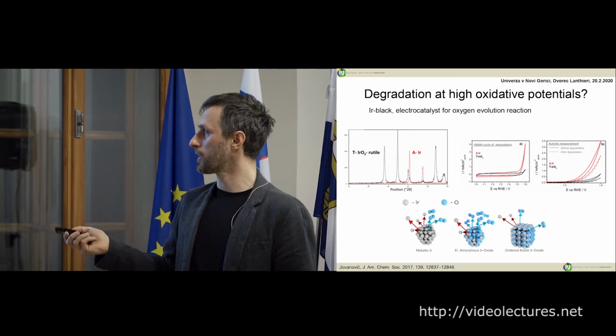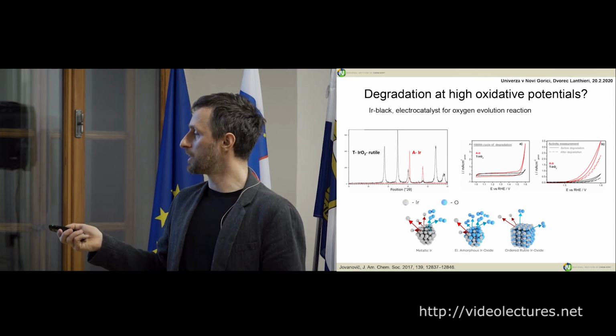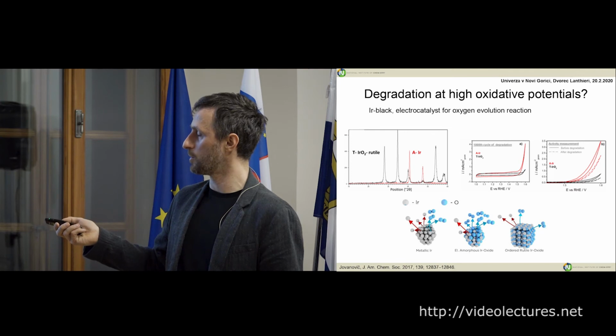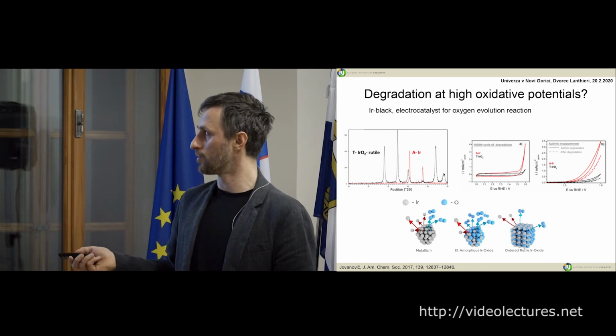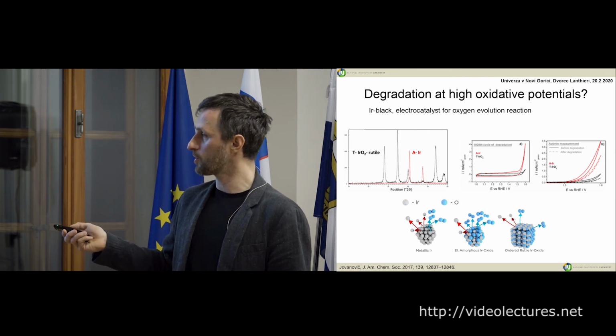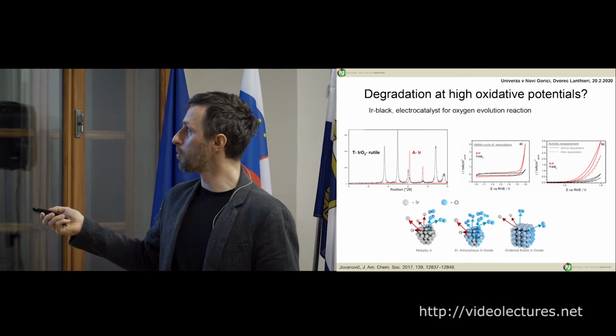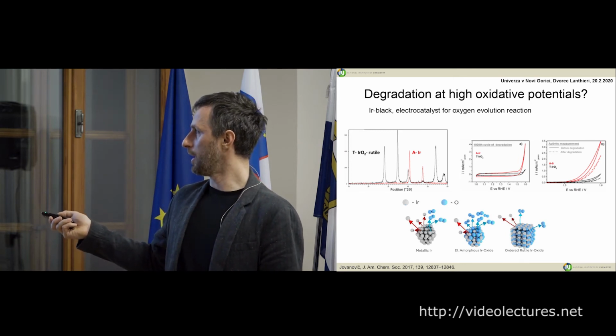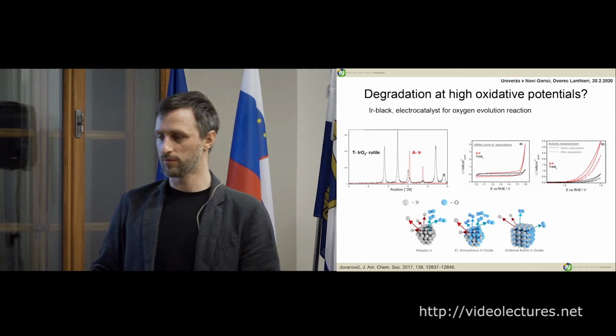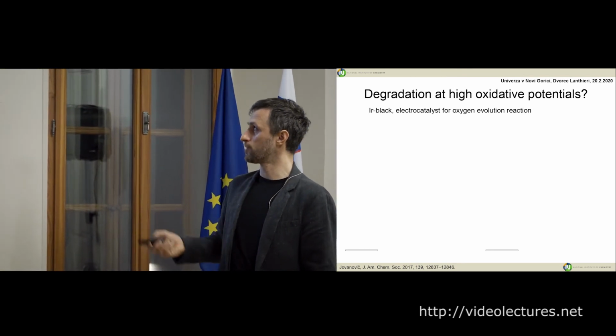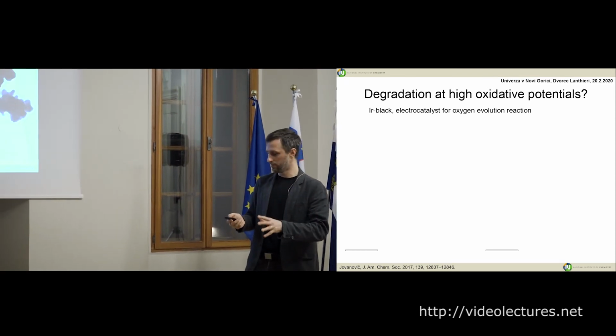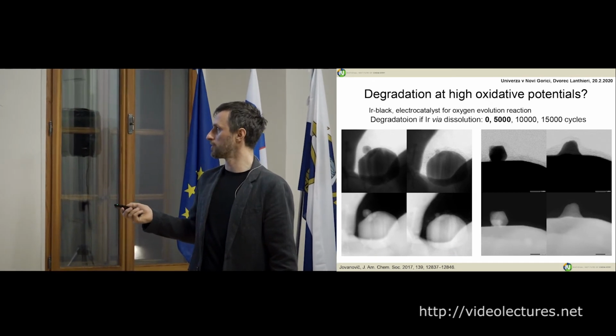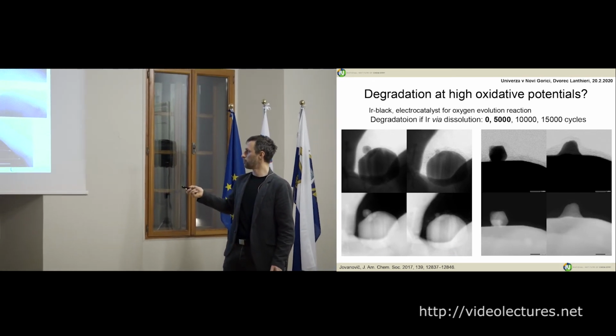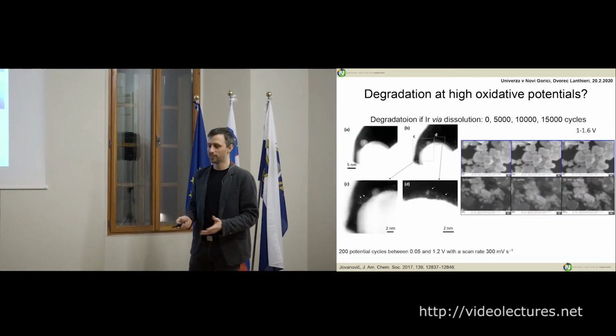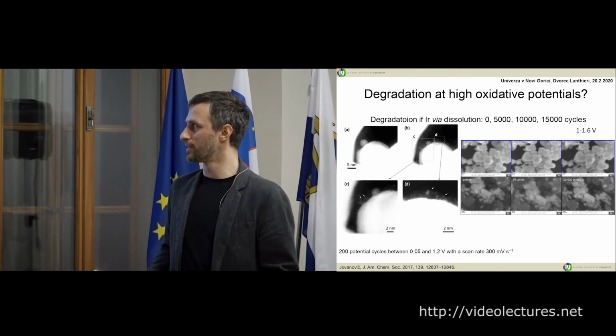Now if we look schematically at what happens, iridium metallic makes a lot of oxygen at these potentials, but it's also dissolving. So the degradation of this catalyst is dissolution. And if you make amorphous oxide by oxidation electrochemically, you make more oxygen, so it becomes more active and more stable. And if you have rutile structure, it's kind of not active. This is how the catalysts look, it's just amorphous. It's just a powder of iridium, you have everything from nanoparticles to different facets, pores, so it's a mess. But this is the catalyst that they use in industry, because it's the only thing that is stable at these high potentials.